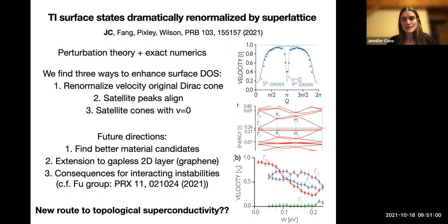And there, what they see, which agrees with our results, is that if you enhance the density of states on the surface of a TI, you enhance the interacting effects. Great, but they go further and in this particular limit compute the superconducting TC and show that it scales polynomially with the electron-phonon coupling, which is an improvement over the usual exponential scaling.